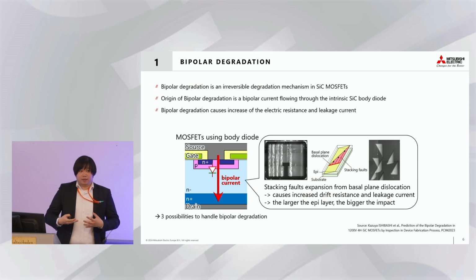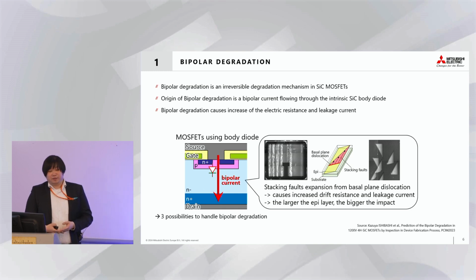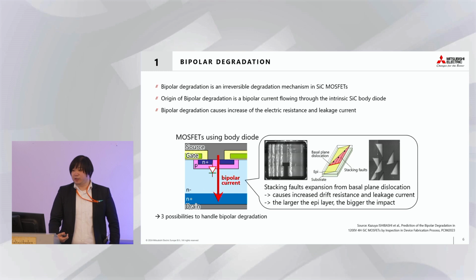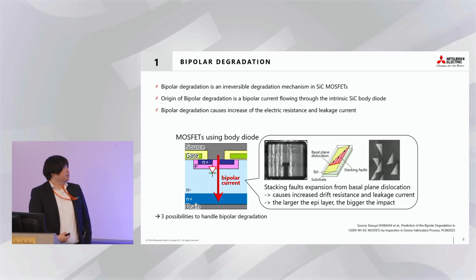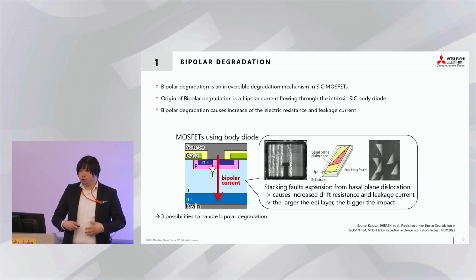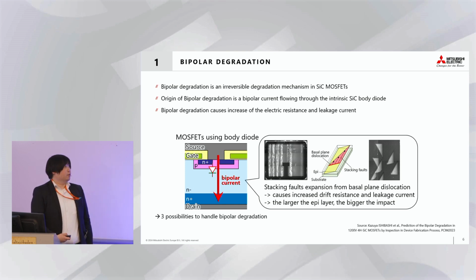So like I said, reliability, in this case, I want to concentrate on the bipolar degradation. Bipolar degradation is, of course, not so good because it's an irreversible degradation mechanism in SiC MOSFETs. The problem is that in reverse direction, we have a so-called body diode in which a bipolar current can flow. And this bipolar current can cause stacking fault expansions from basal plane dislocations, which means if we have this bipolar current flow in reverse direction, there's a risk of bipolar degradation which will cause an increased drift resistance or leakage current or even other risks.